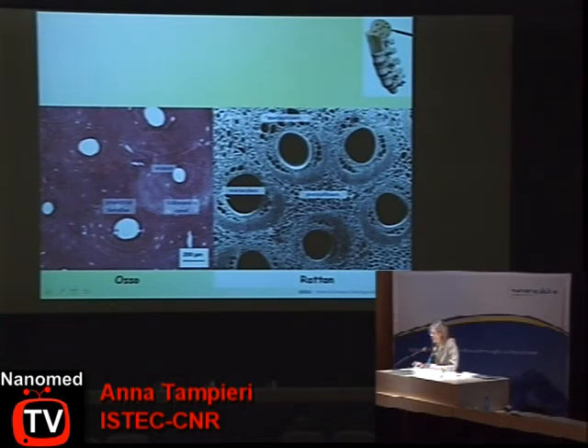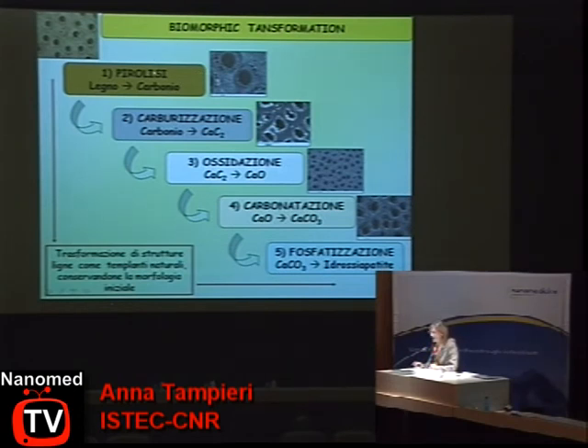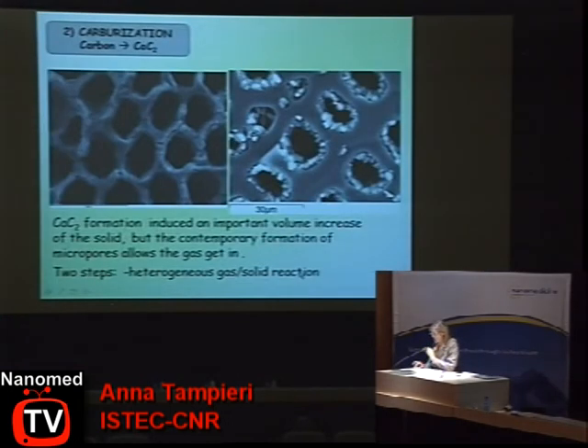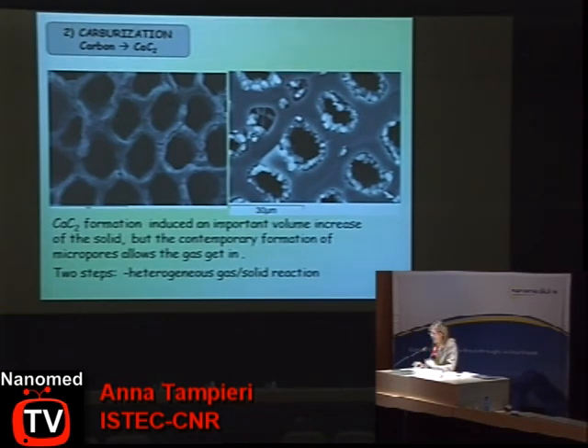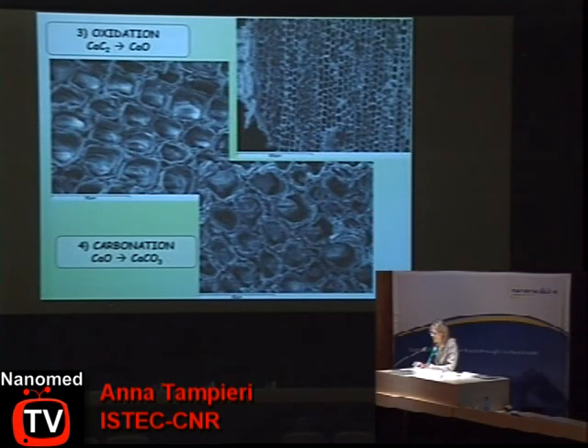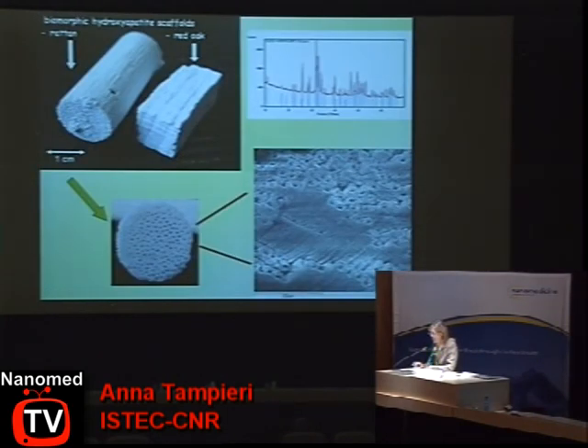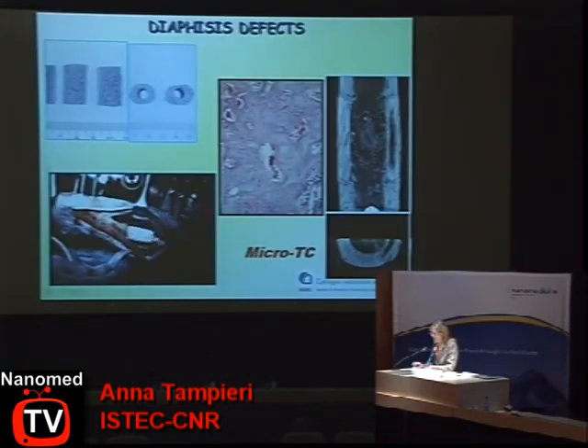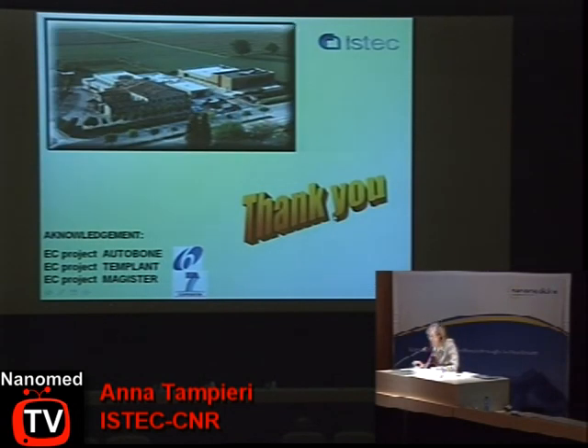This wood was used to produce scaffolds for long bone defects, for load-bearing long bone defects. We set up a complex multi-step process, starting from pyrolysis, carburization, oxidation, carbonation, and phosphation, and at the end, always preserving the morphology and the microstructure of the starting wood, we succeeded in producing hydroxyapatite from wood. This hydroxyapatite has been tested in long bone defects, and as you can see here, we have a very good integration. And I would like to thank the European project which allowed us to do all this work. Thank you.